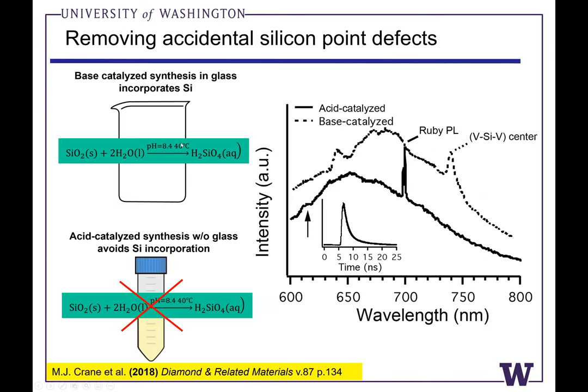So focusing first on the silicon split vacancy center, we had a hypothesis that when we were making our carbon aerogel material, we were actually using a glass beaker and base catalyzed cross-linking reactions in water. And if you've worked in a chemistry lab before, often a base bath is used to etch silica glassware used in synthetic reactions. And so we started to wonder, maybe even at these very mild pH conditions of 8.4 and modest temperatures, around 40 degrees Celsius, maybe we were etching the silica off the glass.